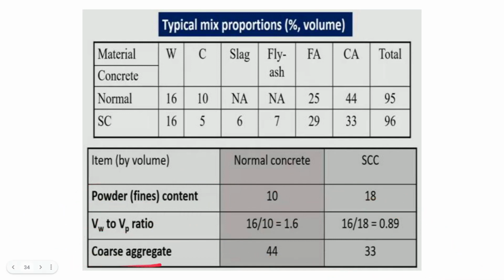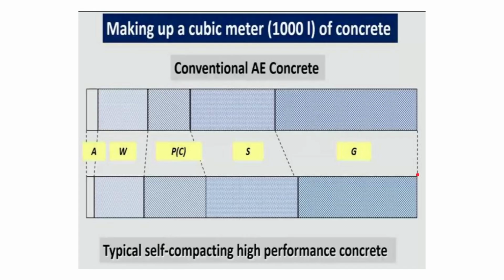So coarse aggregate is, as you saw, 11% less by volume in case of SCC compared to normal concrete. So these are the various parameters. Here they endorse the use of fly ash, pozzolanic materials and other things along with the cement to increase the powder content and reduce the coarse aggregate. And also for sand they use fines. We will see how all those are implemented.